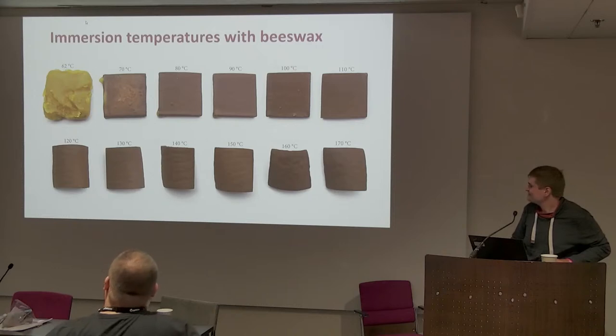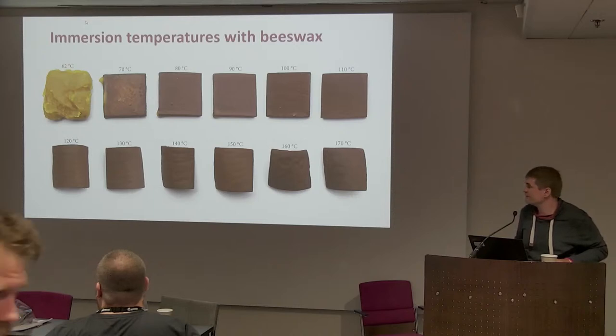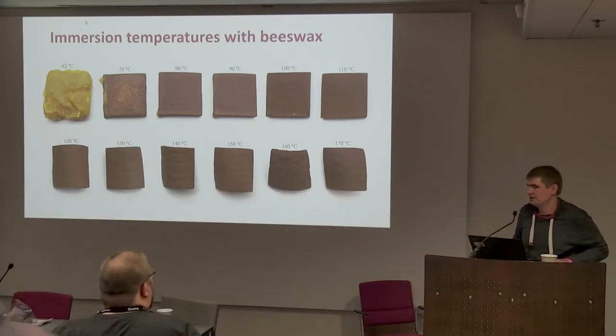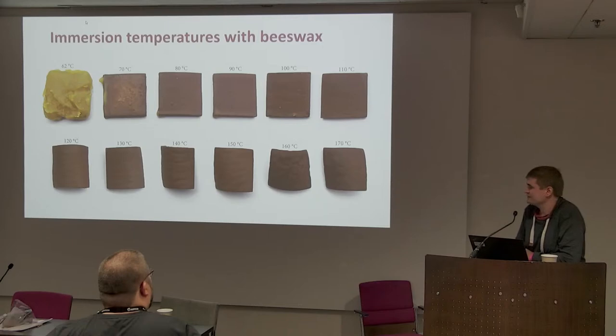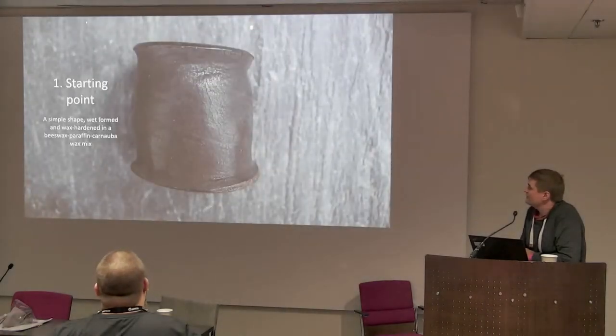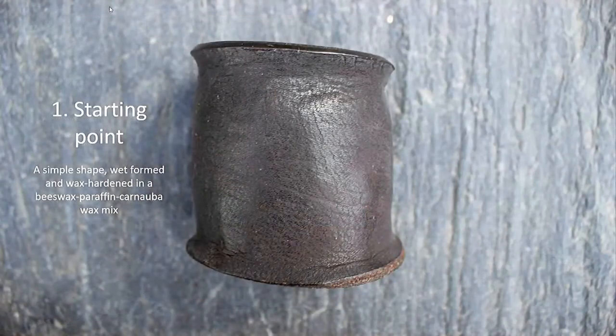Anyway, the temperatures you can use depend on the stuffing agent or mix you're using. For example, with carnauba wax or stearic acid, these temperatures are a bit different. But this goes to show that if you have dry leather, for example at 150, and you don't do an extended period of immersion, it can actually be pretty fine, even though it's a lot higher than the shrinkage temperature of wet leather.